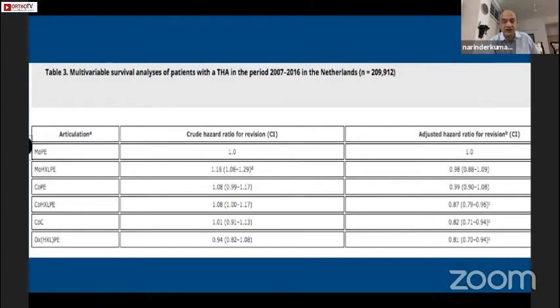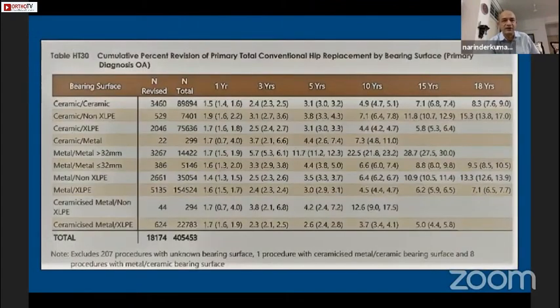So this was only the Dutch Arthroplasty Register. I said, okay, let me explore the Australian registry, the Australian and New Zealand combined registry, of course, which actually showed the similar trends over a longer term. At 15 years, again, it was the ceramicized metal, or the Oxinium on cross-link poly, which had the least revision rates. Again, that was a surprise. Ceramic on cross-link poly was number two, and number three was metal on cross-link poly. So there were no surprises there, except that the Oxinium on cross-link poly has the least revision rate, lesser than even the ceramic on cross-link poly.